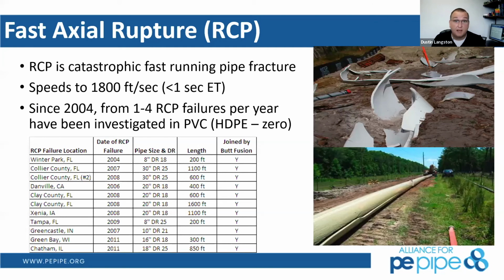RCP, we can talk about RCP. This applies to every pipe material. Every pipe material can have RCP, which is rapid crack propagation. But you have to have exactly the right criteria going on in your system to be susceptible to rapid crack propagation. This is something that we understand all the way through with polyethylene pipe because we are used in natural gas distribution systems. You have to have in compressed air systems great RCP resistance to make sure that you're not going to have some kind of a long running crack if you are struck by a third party backhoe bucket, whatnot.